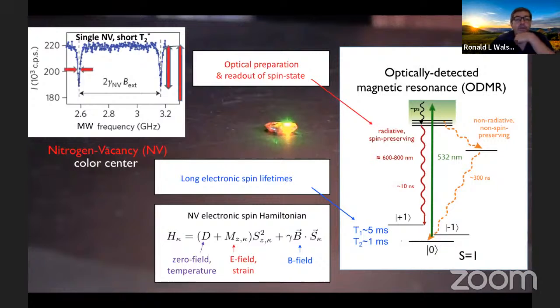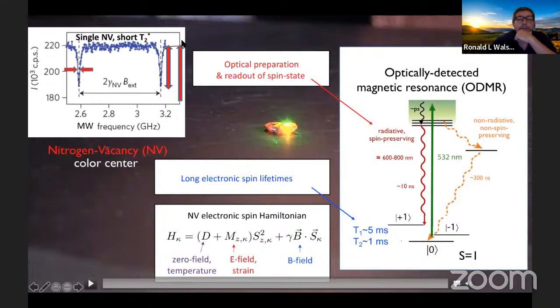Key things here, of course: how many photons are you getting? Shown in red, the rightmost red arrow. What is the contrast? How much is the change from the high fluorescence to the low fluorescence? You want that to be as sharp a change, as big a change as possible. And how narrow are those lines? You'd really like these T2 stars and the T2s to be much longer, so you get very narrow lines. So the more photons, the greater the contrast, and the narrower the lines, the better a sensor you have. The more change in the measurable, the red fluorescence, you have with the thing of interest, let's say the magnetic fields.